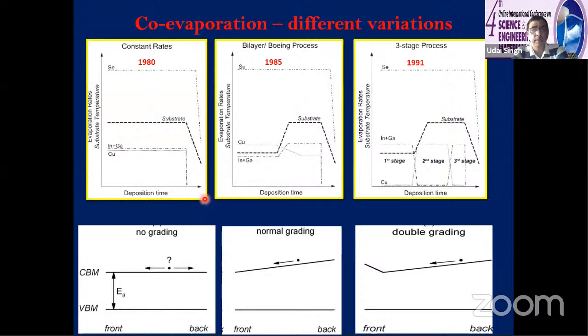So depending on this profile, initially, in the 1980s, it started with depositing copper, indium, gallium simultaneously, and selenium is always there. So this has a limited efficiency. But the Boeing company has given this process, which is the bilayer or the Boeing process, in which they have low indium gallium initially and high copper, and after a certain time they try to increase the indium gallium and reduce the copper. So they have a slightly normal grading band gap.